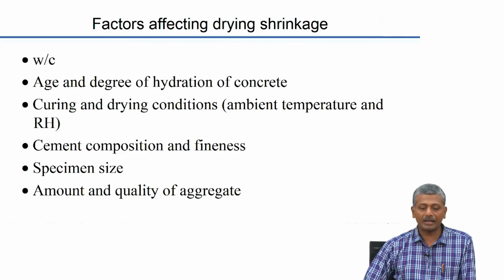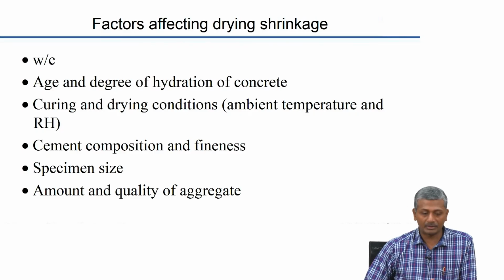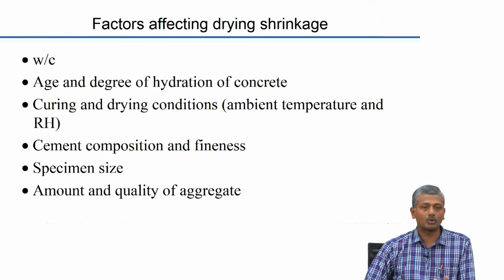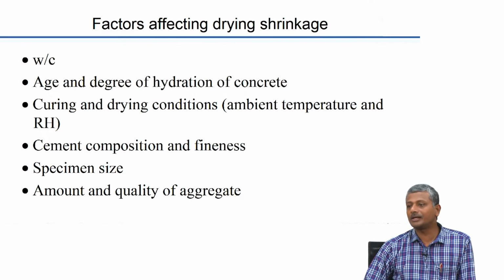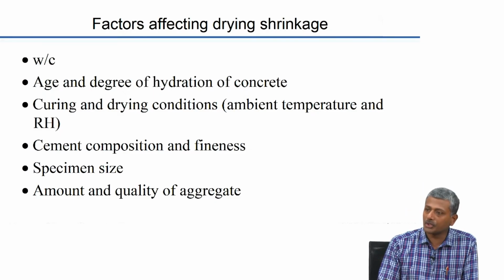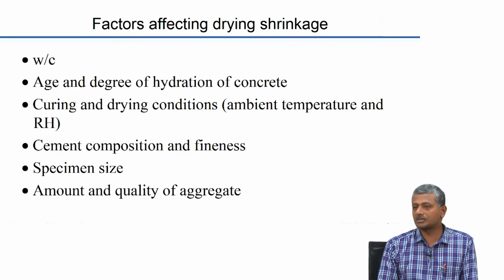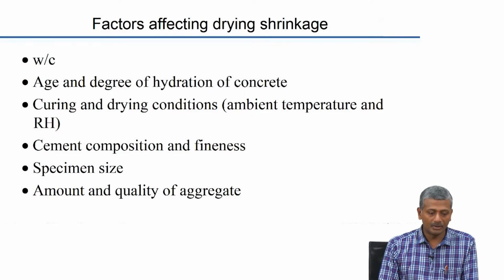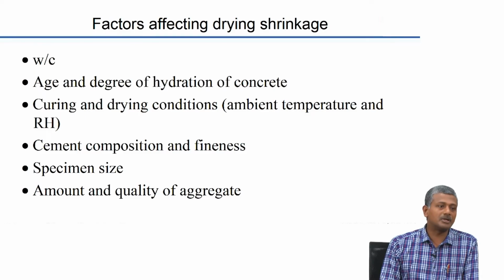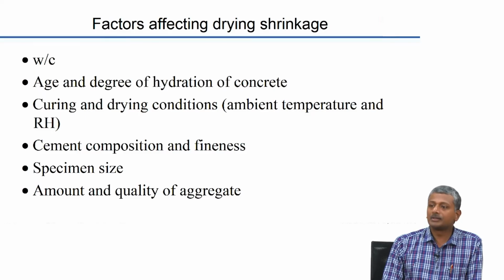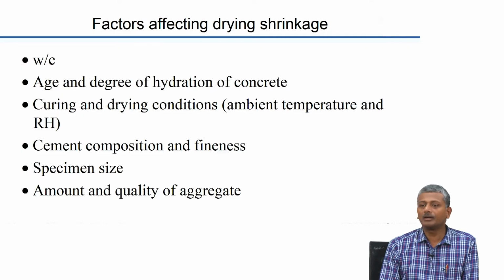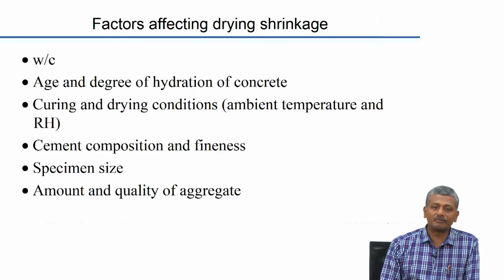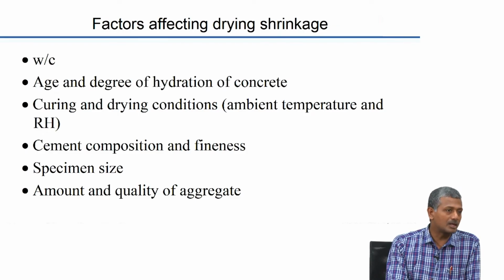So again, I will recapitulate the factors which are affecting drying shrinkage. You have the water to cement ratio, age and degree of hydration of the concrete, right. At younger ages, there is a lot more water in the system, so more shrinkage can happen. If you do long term moist curing, then the extent of drying shrinkage can be reduced significantly. Okay. Curing and drying conditions in terms of ambient temperature and relative humidity are important. The cement composition and fineness is important. Why? Again, cement composition and fineness will have an effect on the amount of hydration that actually happens, and the development of your capillary pore space can depend on that.